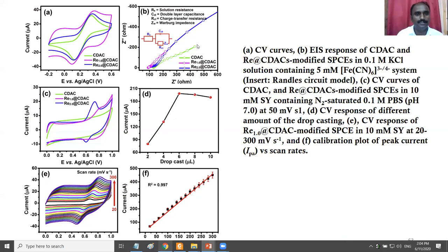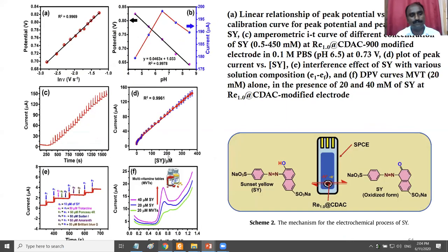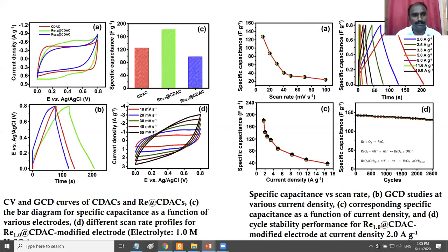This is an EIS profile, the electrochemical impedance spectroscopy studies, and there are also scan rate and pH studies. This composite is further used for electrochemical sensing of sunset yellow. After dipping in the electrochemical solution and passing the current, the hydroxyl group is converted to the carbonyl group, that is OH is converted to O. A proton is transferred during this electrochemical process. And the sensing application is over.